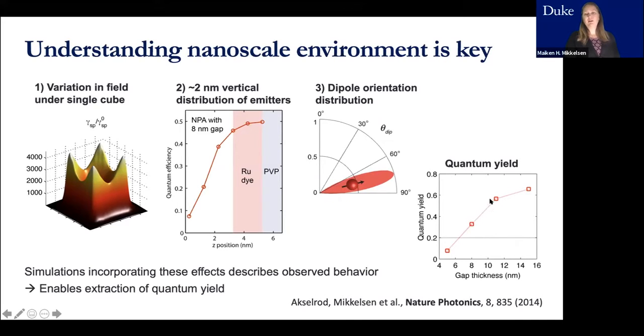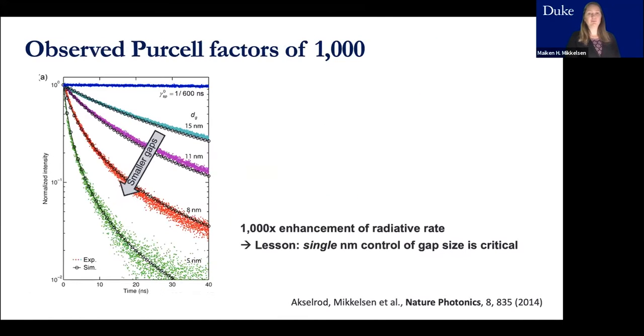But if you add a gap thickness around 10 nanometers, you can get quantum yields around 50%, which is pretty decent for a lot of applications and high for plasmonic structures. So knowing that, now we can go back and look at fits to the data here. This is a stretched exponential fit. So it means that what we are seeing is really a distribution of a lot of different decay channels.